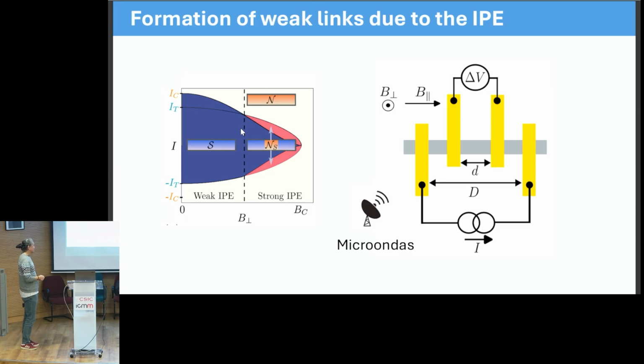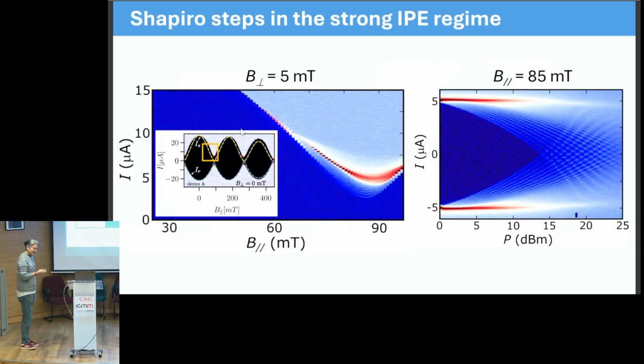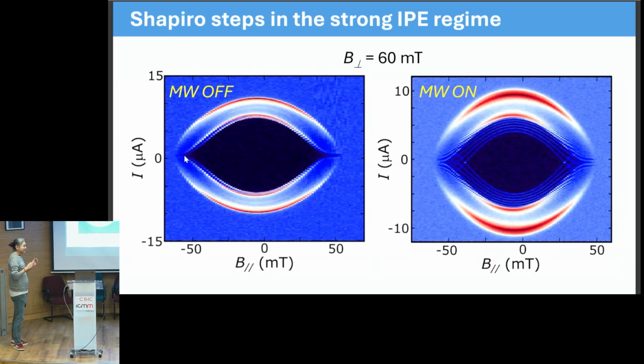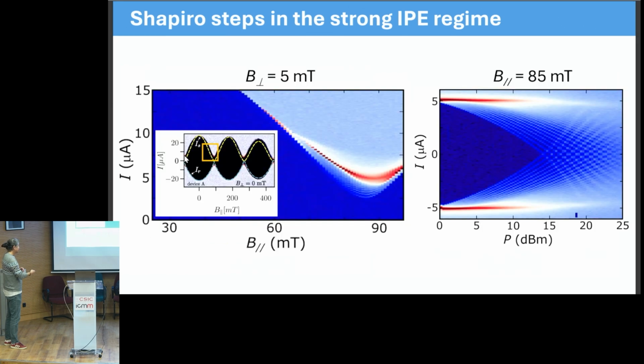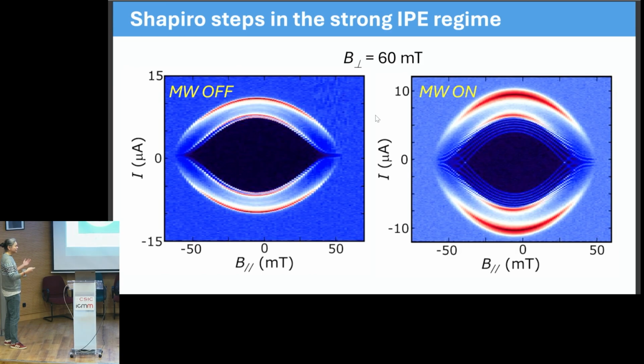I just wanted to mention this is ongoing work, and we can demonstrate the formation of this kind of weak link physics by doing experiments now using microwaves. And we observe the formation of Shapiro steps in some parameter space. Exactly when we are in this region where we can create this weak spot that we observe by transport, we see that Shapiro steps emerge from these regions. And we can now control by means of magnetic fields in which region the system will behave as a weak spot.